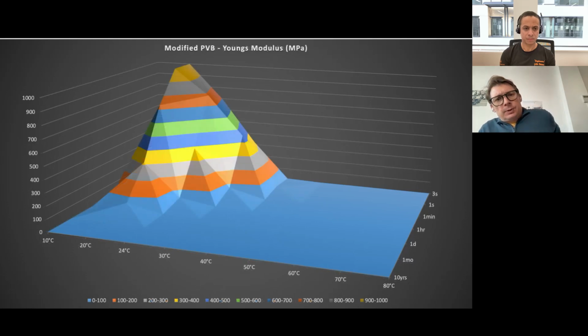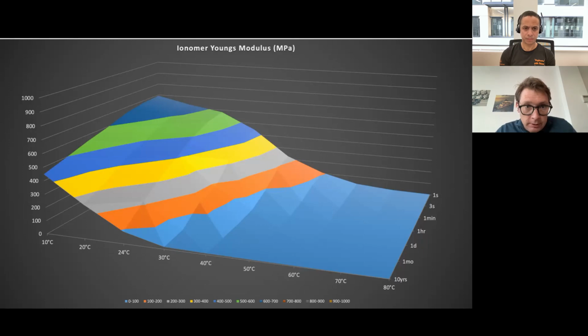But over 23, 24 degrees, we now have a modified PVB, which is much higher stiffness, both at its low temperatures and low time durations, but up to 24, 30 degrees. We also have Kuraray's ionomer material, which has lower stiffness in the shorter term, but much greater stiffness at elevated temperatures and elevated times. So it's a really useful product where we require greater stiffness over a length of time.